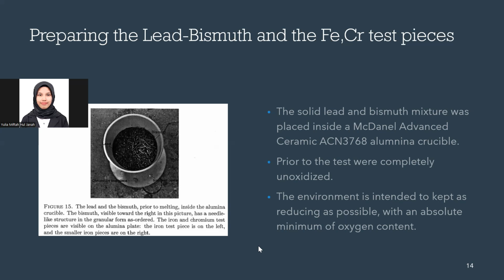For this, the preparation environment is intended to be as reducing as possible, with absolute minimum oxygen content. From figure 15, we can see the lead bismuth in this cup prior to melting, inside the alumina crucible. The bismuth is visible toward the right. This picture shows the granular structure, and the iron chromium test pieces are visible on the alumina plate. The larger test pieces are on the left, and the smaller pieces on the right.